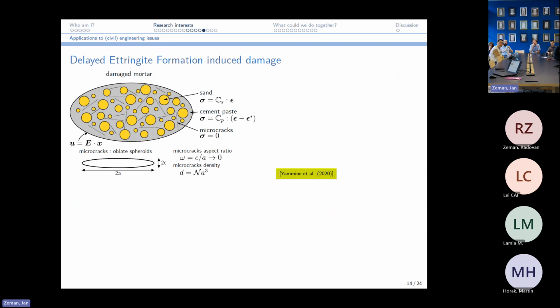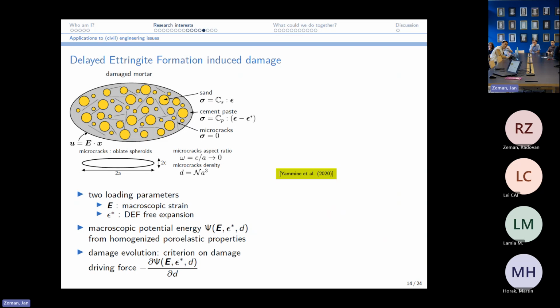But because concrete is heterogeneous and the gravels and the sand do not swell, you have incompatibility of the deformation. So you have microcracking. Okay? So we try to model a bit of that by introducing microcracks and doing that with the mean field homogenization techniques. Right? And so here we had some, I would say, poroelastic setting. So it's purely elastic with some free strain, which is brought by this epsilon star, which is brought by this expansion. And you can compute what is the potential energy as a function of the loading parameters, which are the macroscopic strain and this free expansion, and this crack density parameter. And that involves some coupled terms like in the poroelasticity or thermoelasticity.